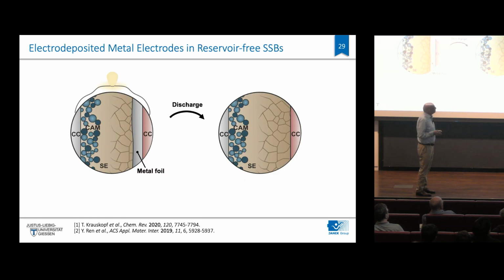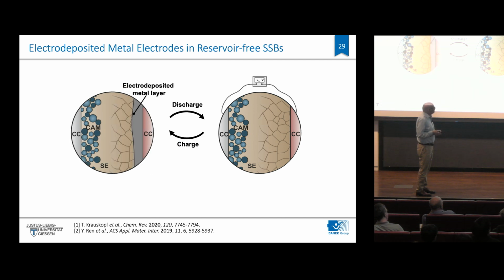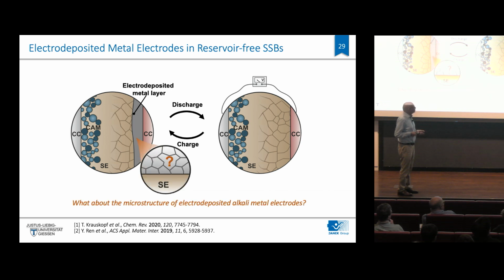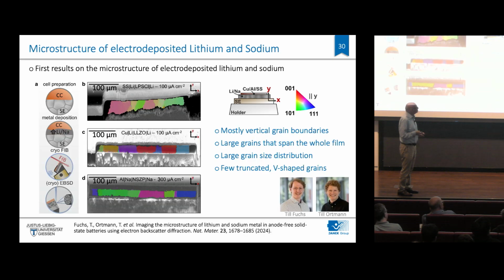Yeah, we went deeper into that and saw, okay, we should really look at how electrodeposited lithium is growing and whether we can control that. So what is really the microstructure of electrodeposited lithium? Nobody had seen that, in fact, before. And this is how it looks for different electrolytes. You might think, okay, this is not very spectacular, but in fact, we found it extremely spectacular because it was the first time one could look into that.